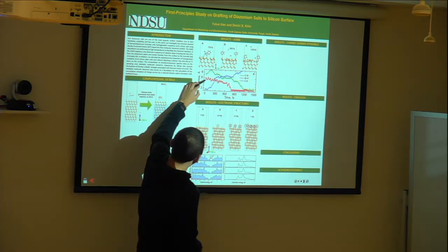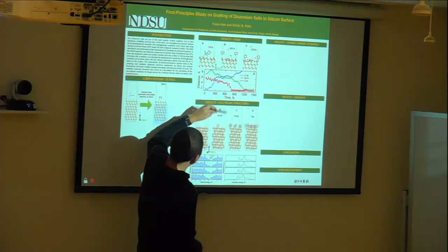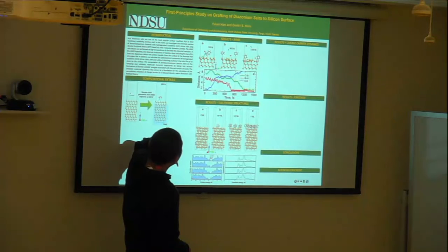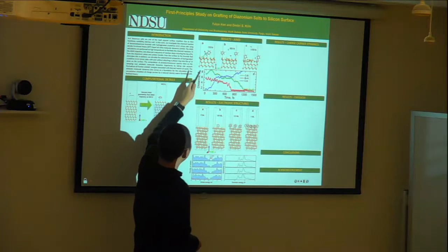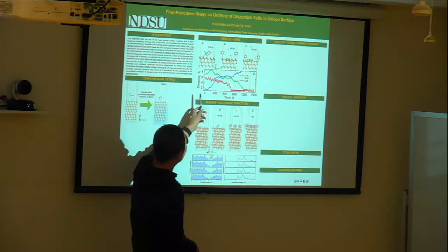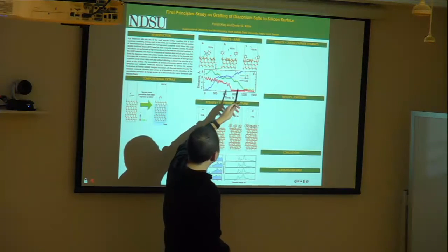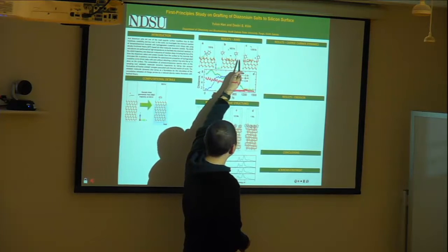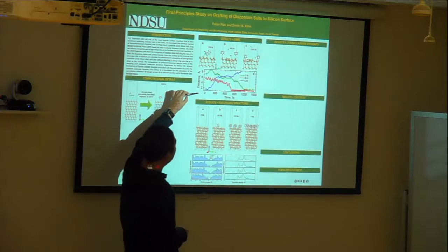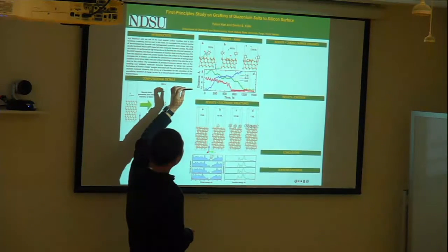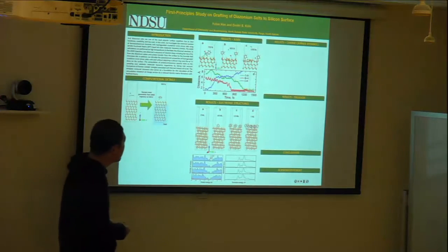Red means the distance between bromine and hydrogen. Green is the distance between carbon and nitrogen. So in the AIMD trajectory, first we observe the breaking of the carbon-nitrogen bond. And as time goes by, we can see the formation of hydrogen bromide. And then finally, we see the attachment of the phenyl ring to the silicon surface. And this AIMD is performed at a high temperature. Because of this high temperature, we can see some surface reconstruction.